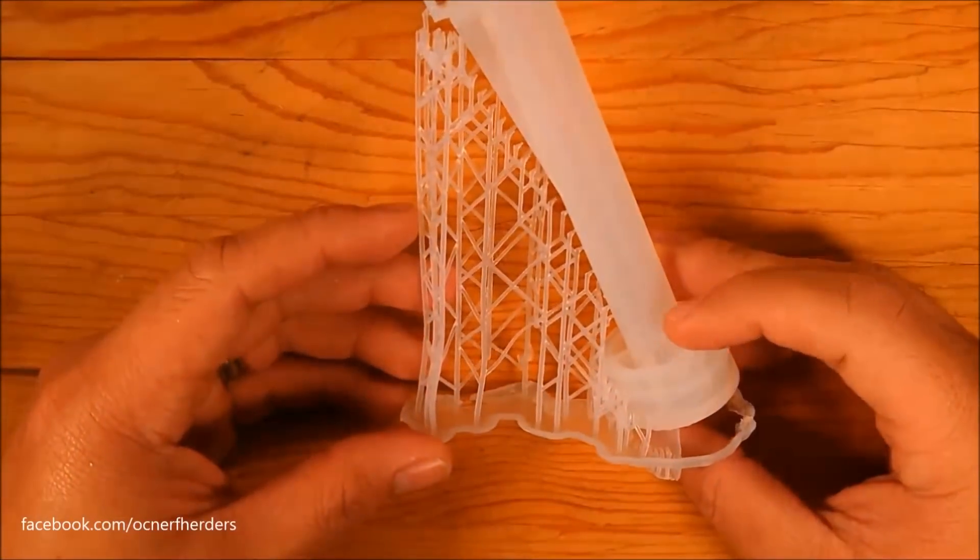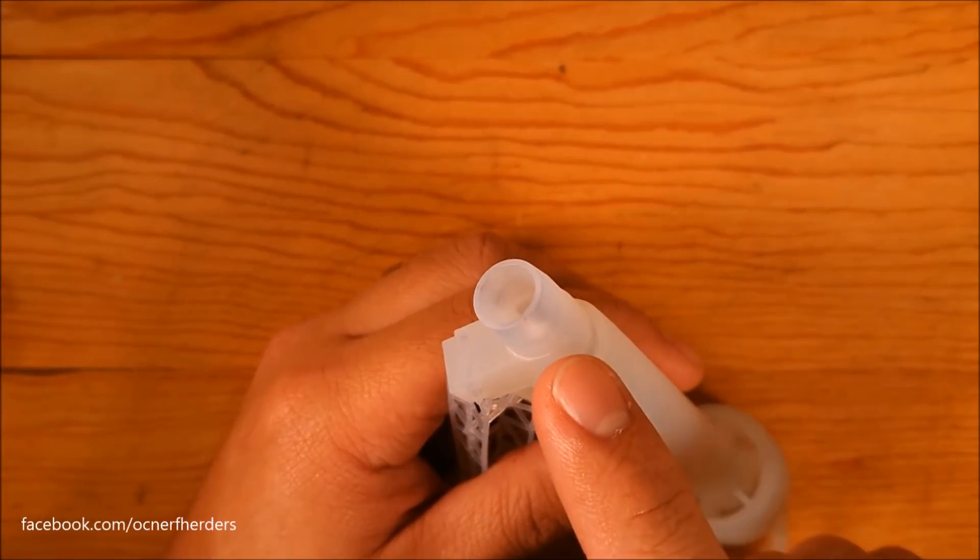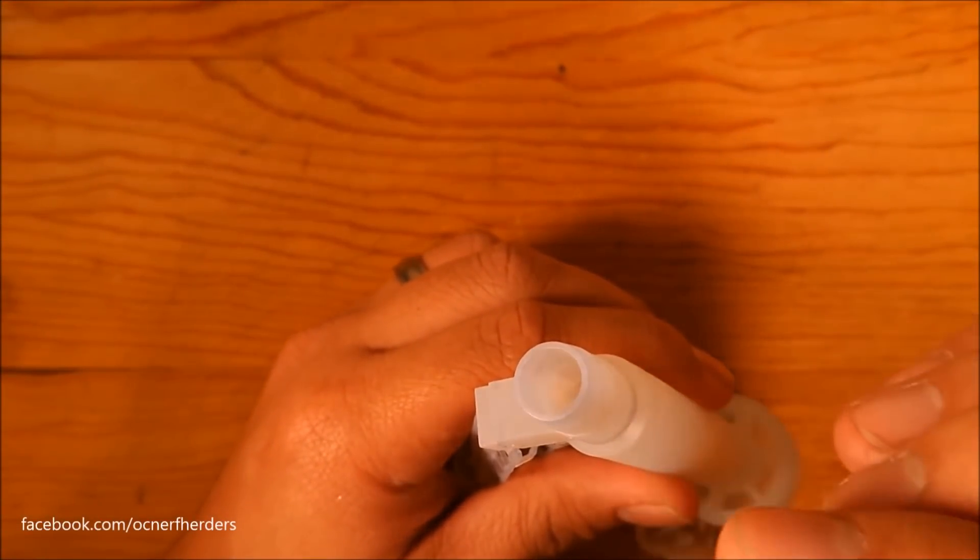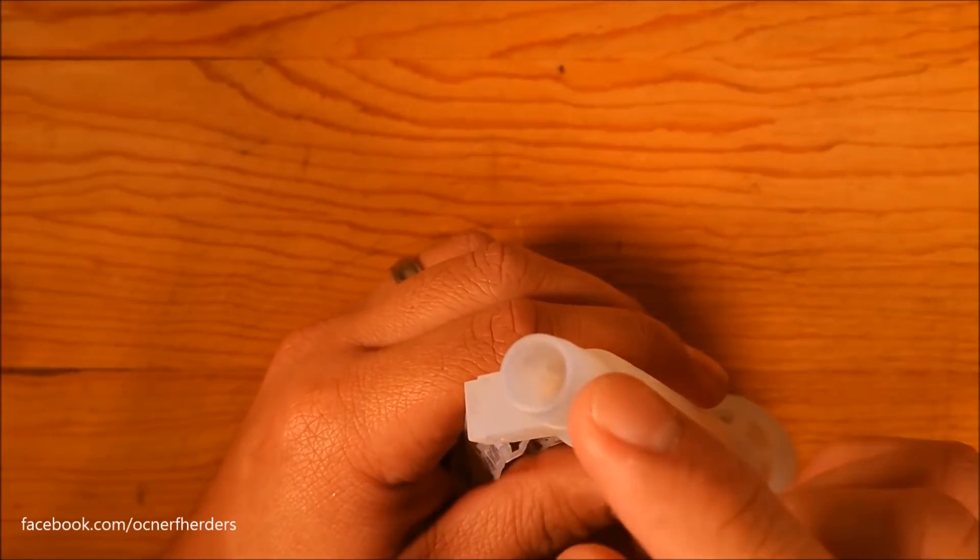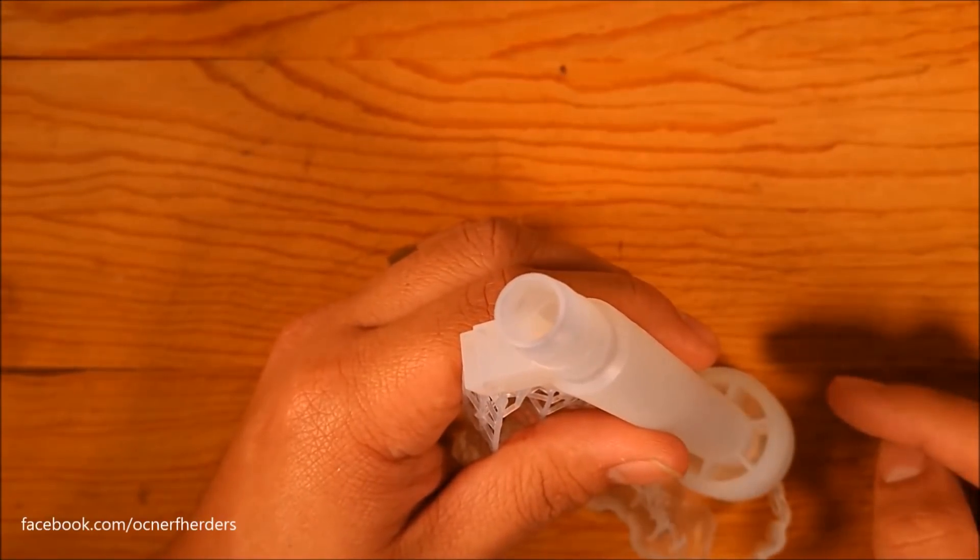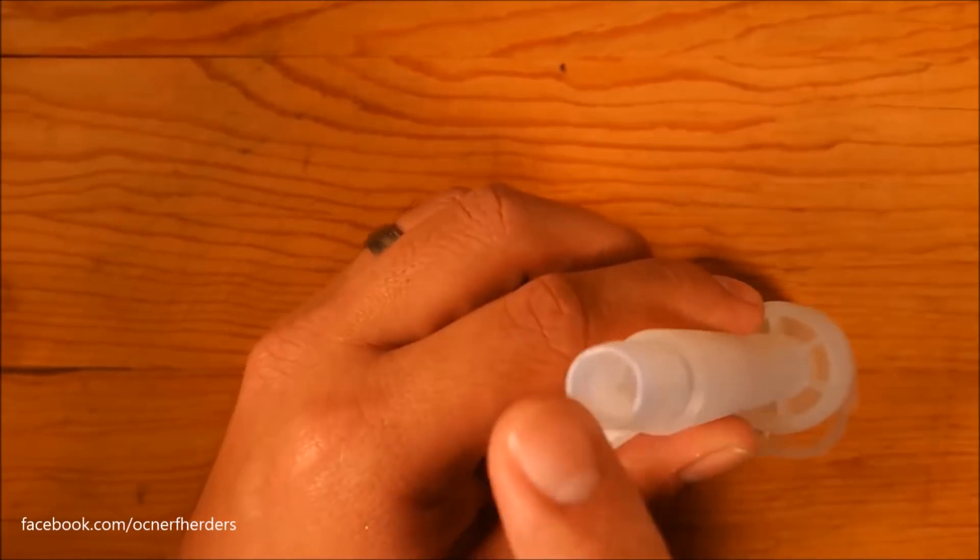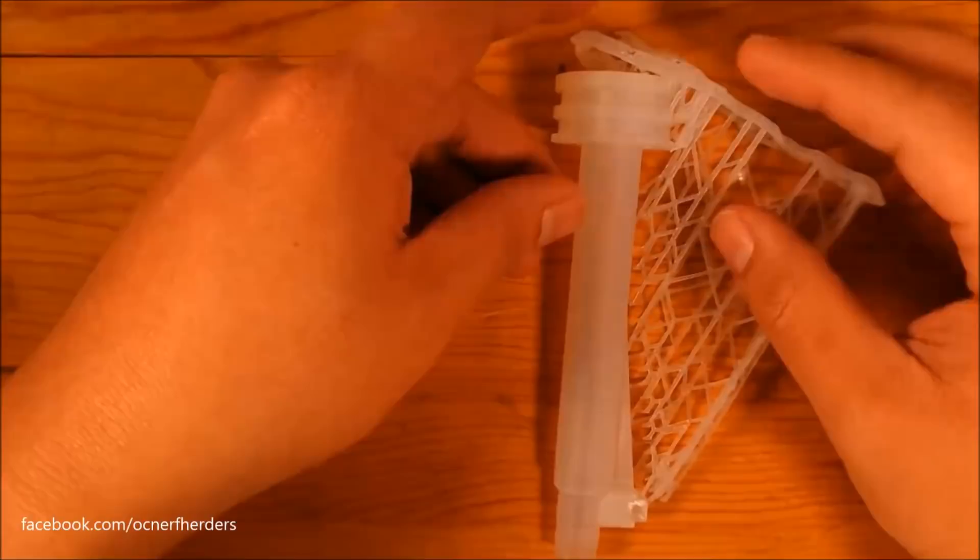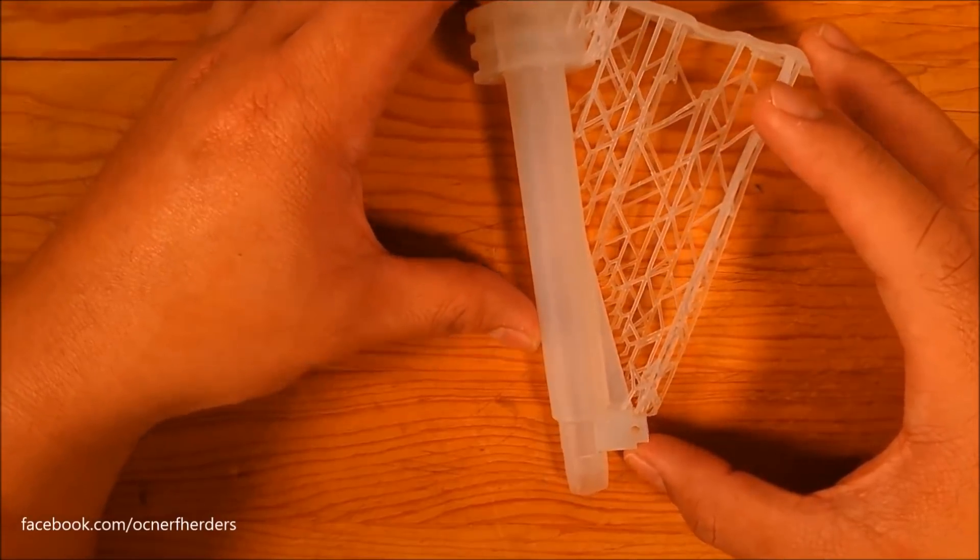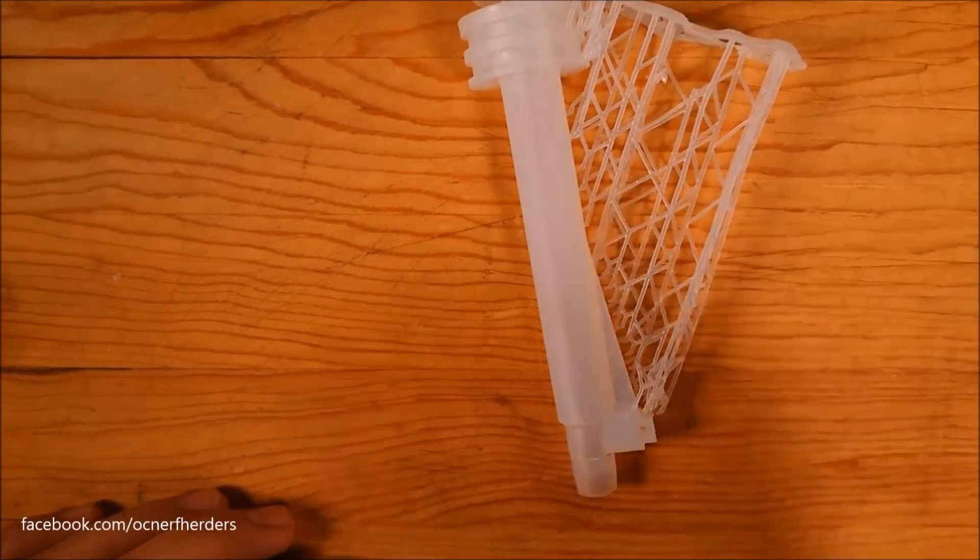I think somewhere on Facebook, I did a video with a bar, a 3D printed rod, and I had printed it in this regard and it was just easy to snap. And then when I printed it in this fashion, it was hard to snap. In fact, I had to put my whole weight on it and it still didn't even snap or barely even bend. And it was the exact same bar just printed at a different orientation. So the orientation of the printing matters in FDM printing. Here, it's a little bit different, a little bit different of a reason. So speaking with June from Orange Mod Works, he had mentioned that the really important focus he had was the accuracy of this part right here, which is supposed to create a perfect seal with 17 32 brass.